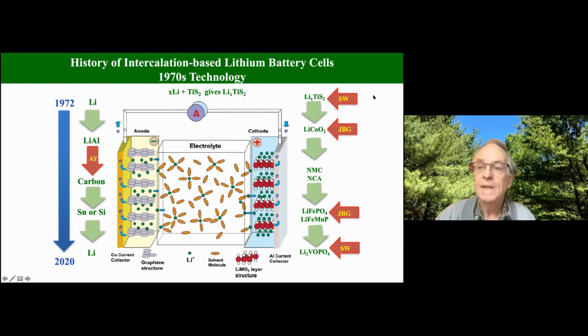On the cathode side, we started with LiTiS2. Then John, who was working on the magnetic behavior of cobalt oxide, recognized it had essentially the same structure, switched to cobalt, and showed that it cycled very well. And this is still the commercial material used in things like cell phones and laptops. Because of the cost of the cobalt, most people have now switched to NMC, NCA, and you heard all about that from Jeff Dahn, who's one of the primary inventors of the NMC materials.